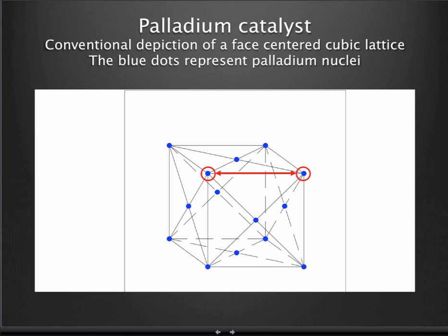The space along each edge of the cube between the vertex nuclei and the two adjacent face-center nodes, of which there are 12 instances, one for each cubic edge, constitutes 1/4 of an octahedral space formed with 3 adjacent cells, so that for each cell in the lattice interior there are 4 octahedral spaces.